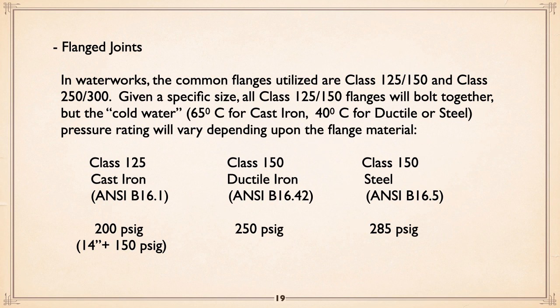ANSI B16.1 basically allows 200 psi if you're using those flanges. Ductile goes to ANSI B16.42. You're good to 250 pound with class 150. And as I say, 125, 150 will bolt to each other. And in steel, which is ANSI B16.5, you're up to 285 psi. Note at class 125 cast iron, the rating goes down at 14 inch or over to 150 psi.